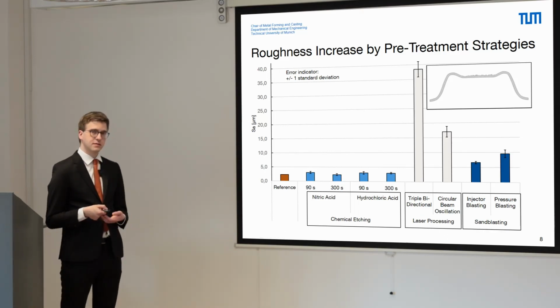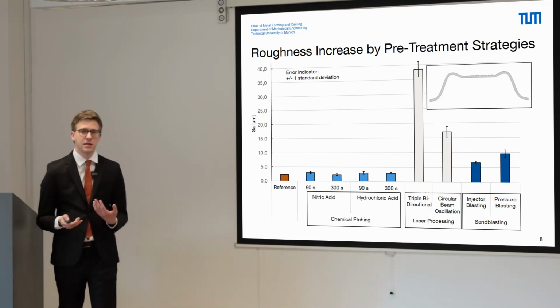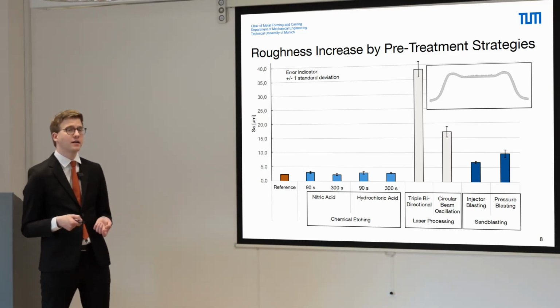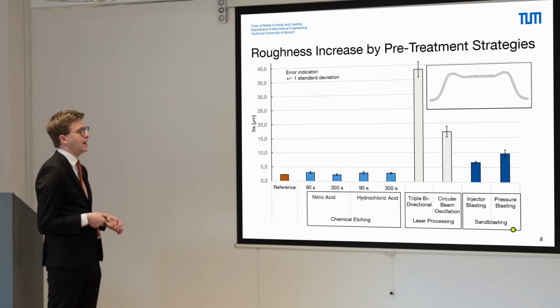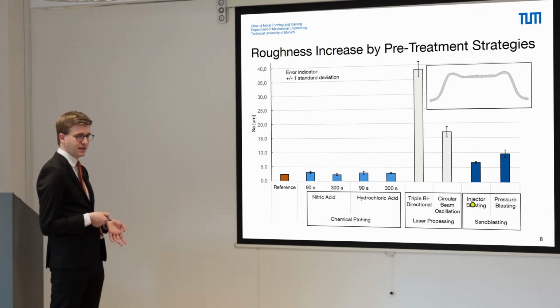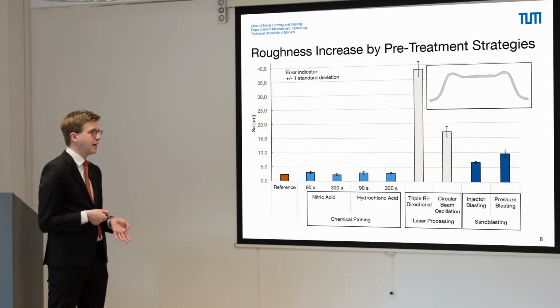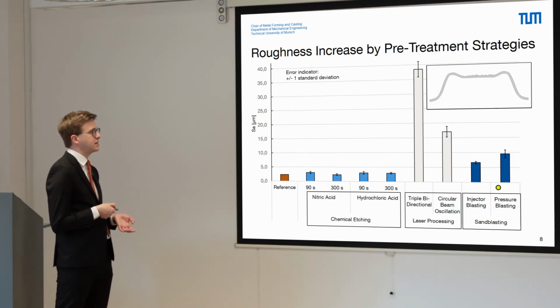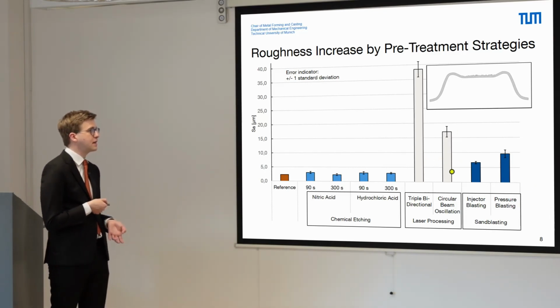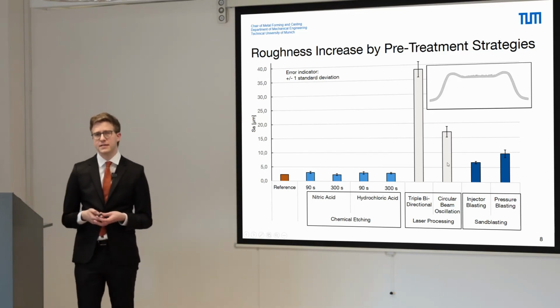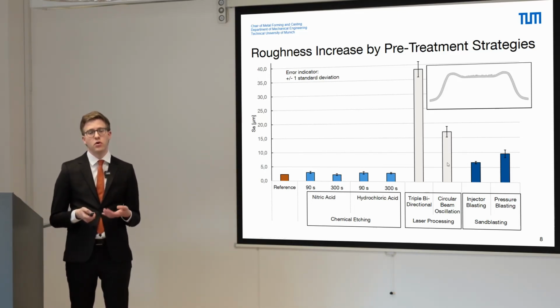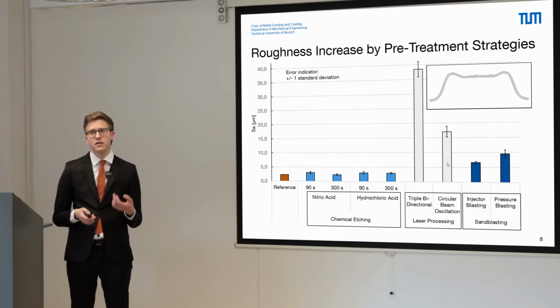The last pre-treatment strategy we examined was sandblasting, and we used both injector blasting and pressure blasting, and even so the effect is not as strong as the laser processing. We will see in the subsequent slides that we were able to generate a sufficient bond strength, so we identified two different kinds of processes for industrial use of the pre-treatment strategies.